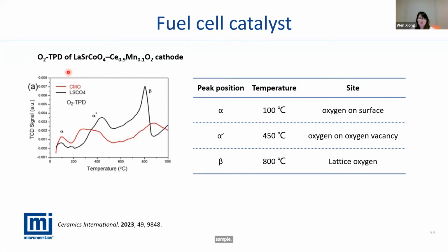Here is an example of oxygen temperature programmed desorption, also using our AutoChem as a powerful tool to study the oxygen species adsorbed on the surface. From the left figure, we can see the oxygen desorption peaks have been divided into three different temperature ranges. For the lower temperature range, we see the oxygen adsorbed on the surface, how many oxygen have been adsorbed on the surface.